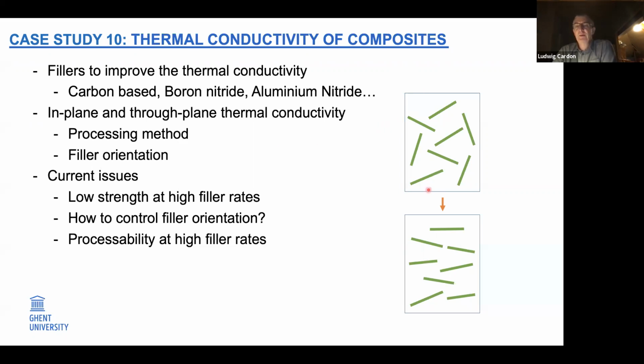Briefly explained. When we have a matrix material with fillers, as you can see here, the most ideal would be a blend like that, because then we have a through plane and an in-plane thermal conductivity, which would be better and which will improve the thermal conductivity of a polymer. This would be, let's say, short carbon fiber or carbon nanotube fillers. But what happens when we do extrusion processing to make plates? Well, the big problem is the fibers will reorient in the flow direction. So we investigate that also on morphology level by extrusion and injection.